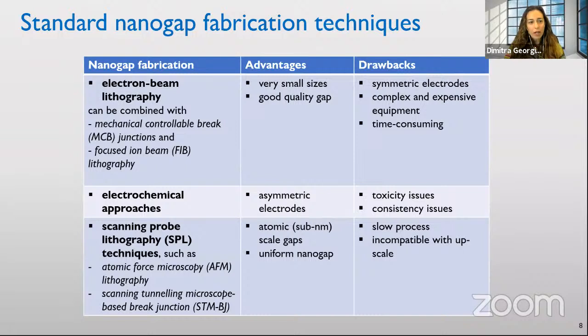Then there are electrochemical approaches, which are scalable, and we can also make asymmetric electrodes. However, sometimes there are toxicity issues with the solvents used, and there may be consistency issues because the nanogaps one can get with these techniques are not always homogeneous, and they have many protrusions that change the performance of the